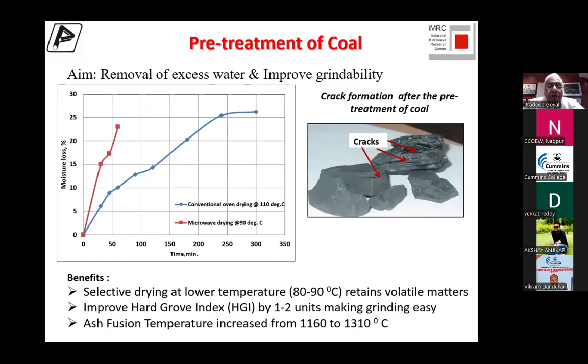So when we process the coal in the microwave, we were able to take away all the water from the coal. But at the same time, an interesting thing happened: because of the disproportionate heating of coal and water, the whole coal cracked. You can see how the cracks appeared. Now this hard coal, which was very difficult to grind, became very pliable for grinding also. So we achieved two successes here. One, removal of water, and two, making it easily grindable.